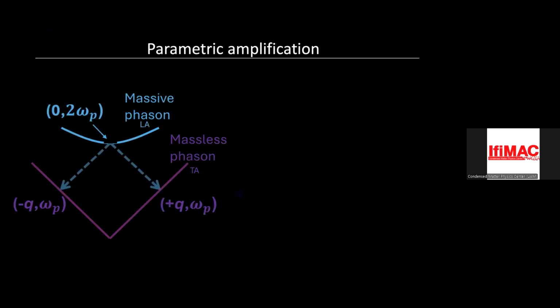But the problem is that this strange temperature dependence that I was talking about is only expected for a massive phason and not for the amplitude mode. And in any case, there are reasons to think that we don't actually see the amplitude mode with the STM. So there are mysteries. After thinking about it for a while, we came up with one possible idea. There's something called parametric amplification. It's a complicated sounding name, but actually in reality, it's a really simple thing. The idea is that you have this particle, which is your phason, and it splits into two.